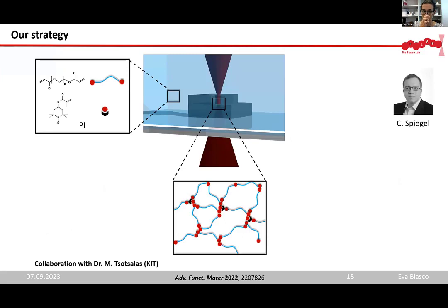So again, coming from my background as a polymer chemist, here we exploit alkoxyamine chemistry. So here the formulation is very simple. We have a dye linker and a TEMPO that very often is used as a radical quencher, but this TEMPO has a photopolymerizable group. So we can incorporate it.